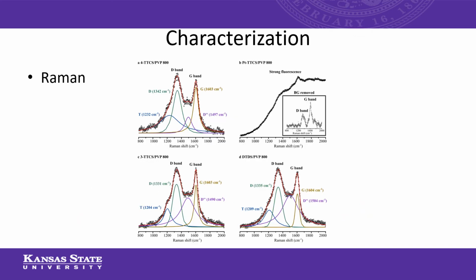Raman spectroscopy, we were not able to obtain a good signal from platinum TTCS sample. You will see a very strong fluorescence, and I believe this is coming from platinum. But after we remove the background, you'll see the G band has a much stronger signal than D band. This can be explained from the XPS.